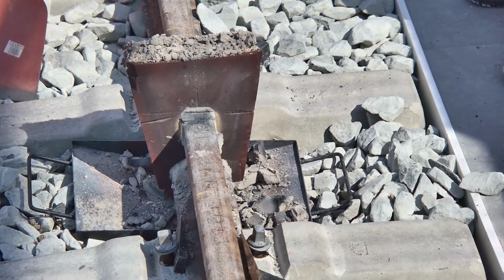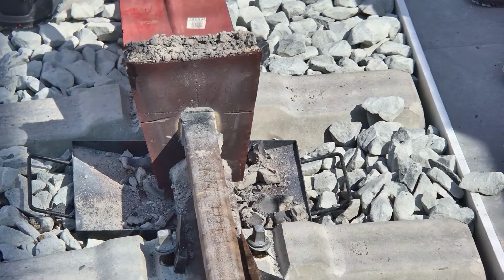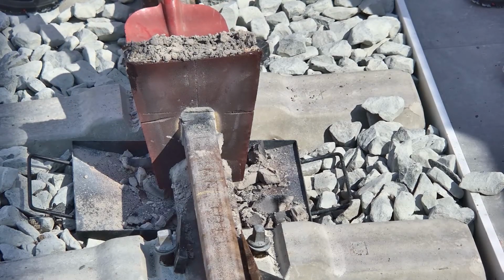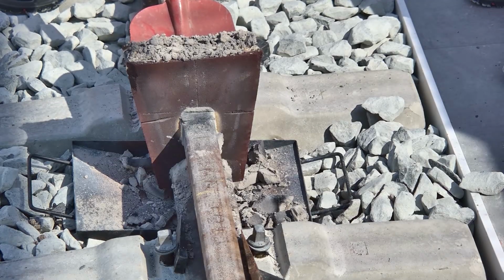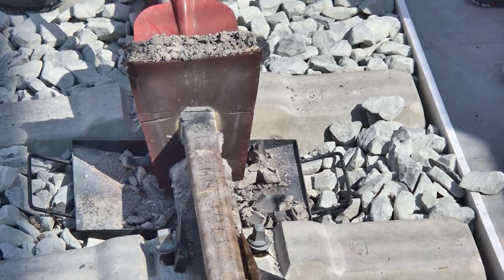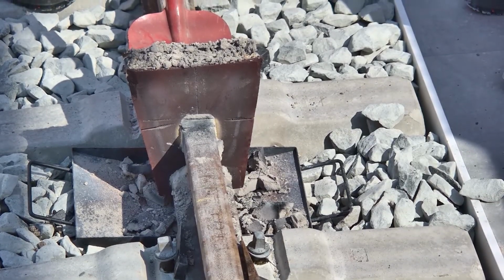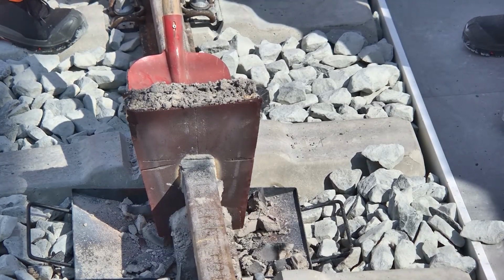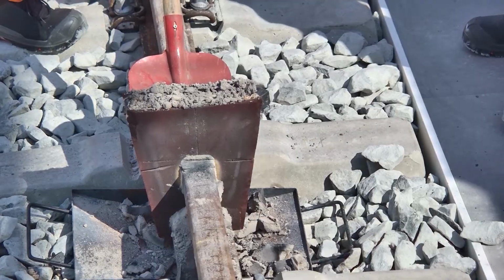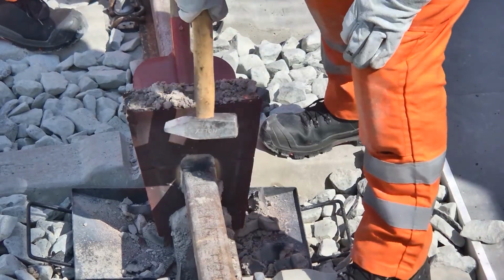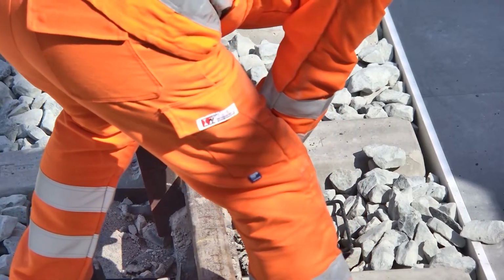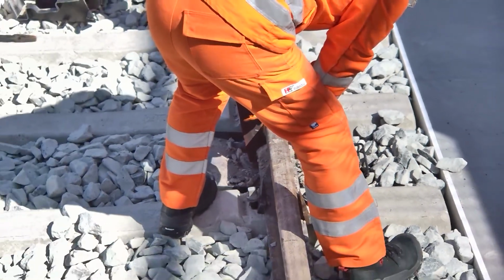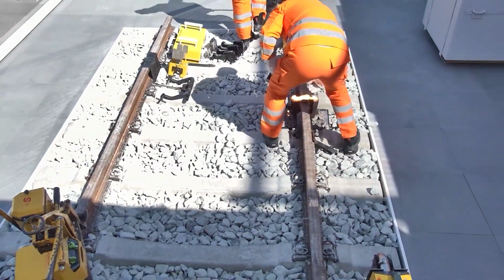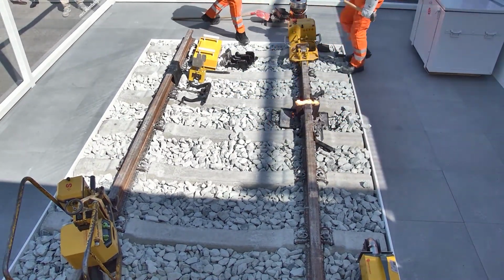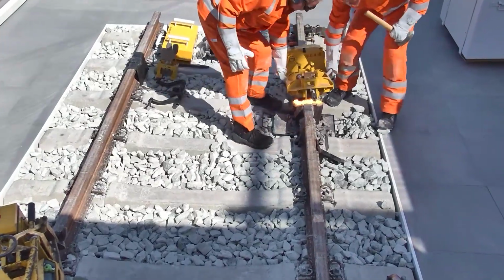And for this reason, our weld shear has a pressure force of more than 20 tons to be absolutely sure that we can go through the weld at a stable speed, regardless of how wide it is, if it's a wide gap weld, for instance, and regardless of the procedure or process that we employ. And it's also to be noted that the weld shear is powered by the same battery as all the other tools. So it's a commercial battery that can be purchased anywhere from our partner at Ego. And this powerful battery powers all of our tools.